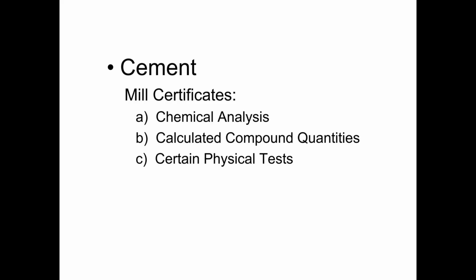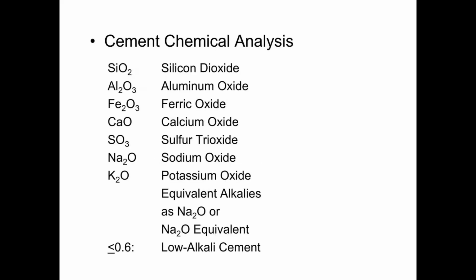So let's look a little bit at the chemical analysis. There on your screen shows some of the oxides that are generally going to be shown on the mill report as far as what proportion of the overall sample was represented by each of these oxides. The sodium oxide and the potassium oxide are the two oxides that contribute generally to reactivity, if there's going to be any reactivity between the aggregates and the cement.